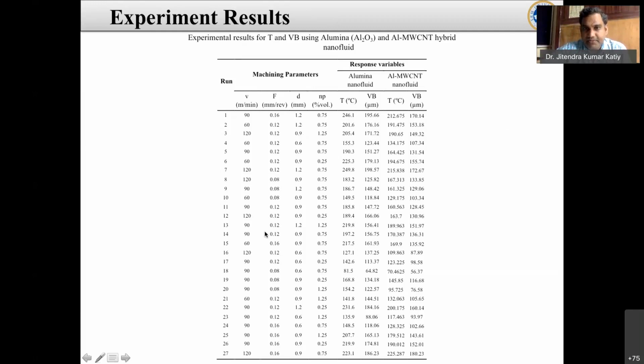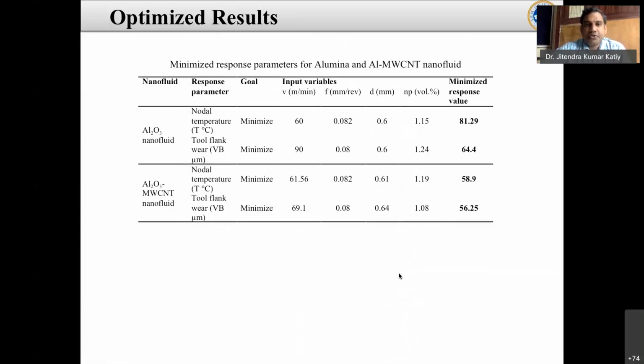In this study, we observed each and every parameter to find where we get the lowest temperature at the zone and the lowest flank wear. We observed that 90 meters per minute, 0.08, 0.6, and 0.75 nanoparticle concentration give the better result in terms of temperature and flank wear. For minimizing the response parameters, in the aluminum nanofluid the goal is to minimize the input variables, and the minimized response observed is 81.29. In the case of the hybrid nano cutting fluid, we get a nodal temperature of 58.9 and the tool flank wear is less.